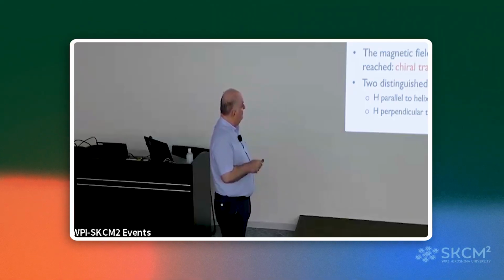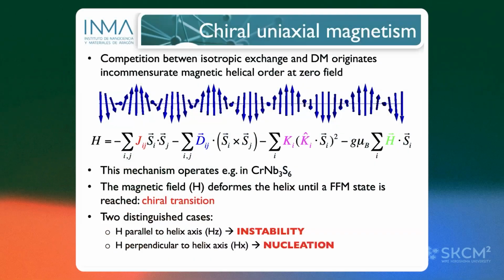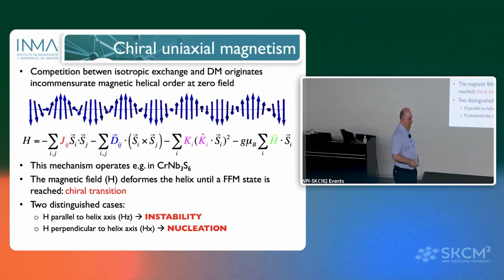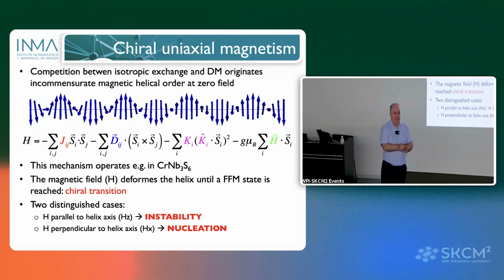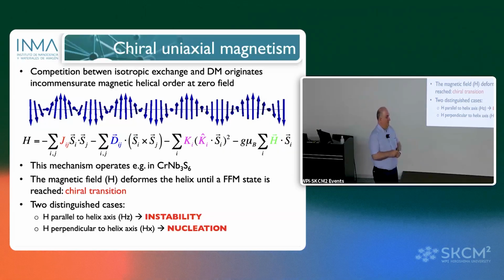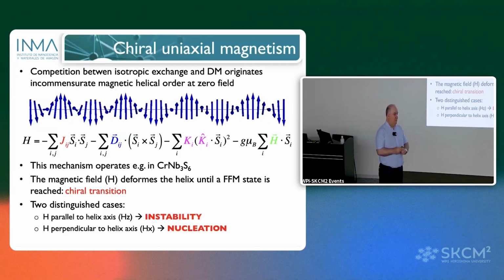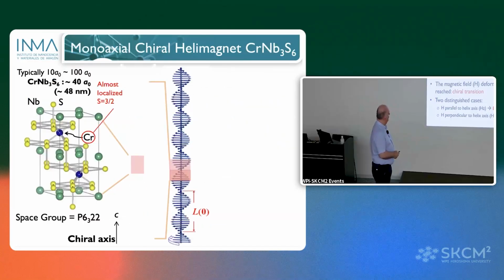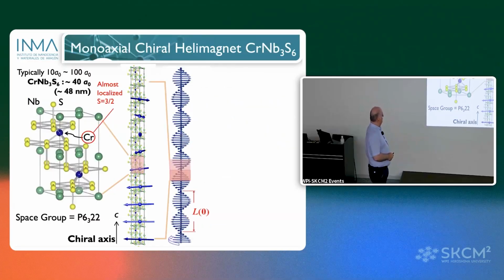Then, if you apply the magnetic field perpendicular to the chiral axis, that means like this, then you will have a nucleation phase transition. In both cases, at the end, for a large enough magnetic field, you will have a ferromagnetic state, but in one case, the mechanism is you are closing a cone, and it's an angle that is going from 90 to 0, and in the other case, it is a period that is going from a given value to infinite. This can be seen in this example.